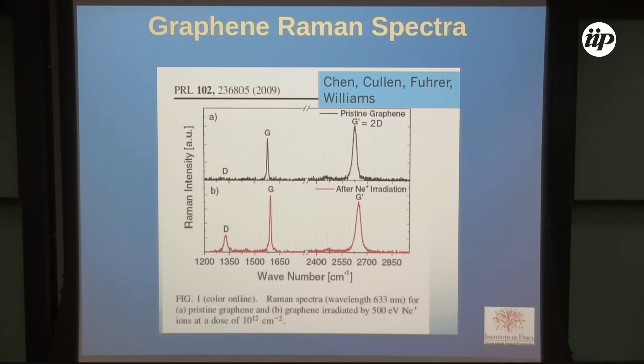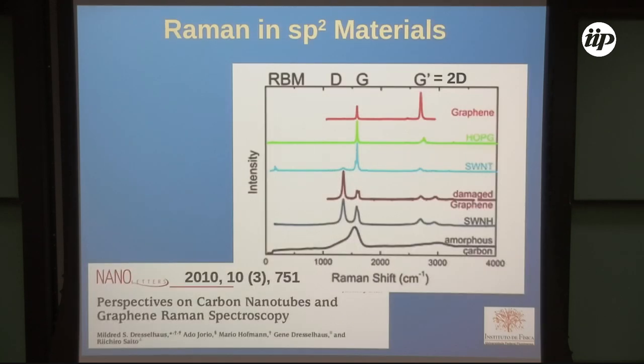So a more recent work. Here we have graphene already in 2009, and this is pristine graphene. We see the G peak, and also this peak, which we now call 2D because it has approximately double the frequency of the D peak. So we call it 2D. When they irradiate pristine graphene, the D peak appears. Okay, so what's happening?